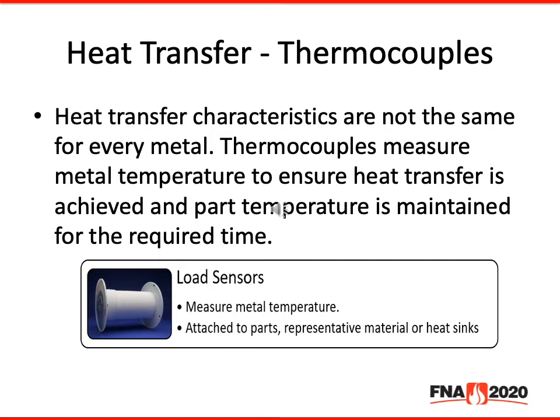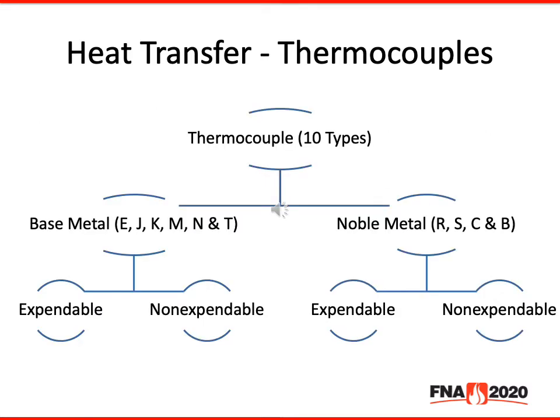Some industry specifications require that parts be held at temperature for, say, 30 minutes per half inch of material thickness. This is a consequence of heat transfer. If a material is not held at temperature long enough, the product will not reach the desired temperature throughout and, therefore, will not have homogeneous properties throughout. Product temperature is measured using thermocouples, which is covered extensively in AMS 2750.